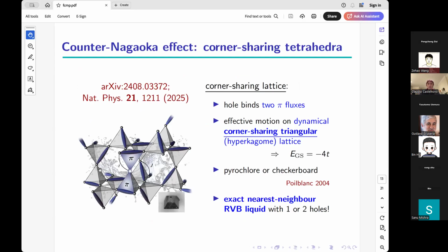On a full lattice, shown a portion of it here, something somewhat spectacular happened. The hole at this site is able to resonate simultaneously with two triangular plaquettes where it shares a singlet with the top tetrahedron and a singlet with the bottom tetrahedron. And it's able to hop freely around these two triangles. And if it hops, let's say that we hop the hole here and the singlet goes here, then it's able to resonate with this face. And so the hole is able to move on a corner-sharing triangular lattice, which is embedded in a pyrochlore background.